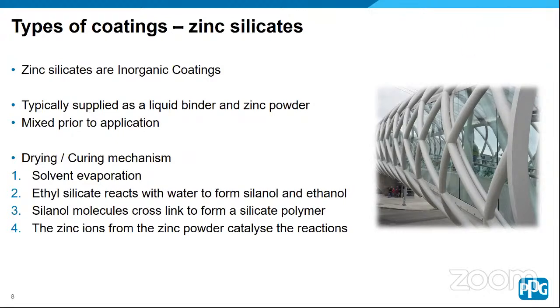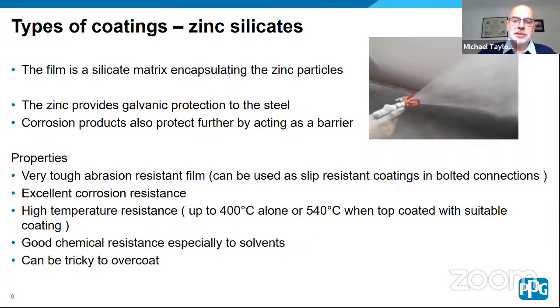Drying and curing mechanism, and you have the solvent evaporation first, and then the ethyl silicate reacts with water to form silanol and ethanol, and then the molecules cross-link to form a silicate polymer. And the zinc ions actually also catalyze the reaction as well. There are water-based zinc silicates as well, but this presentation mainly concentrates on the solvent-based ones. The film is a silicate matrix, and the zinc particles and the zinc dust are encapsulated into that matrix. And the zinc, as Martin mentioned, provides galvanic protection to the steel. With also, when you do get corrosion, some of the corrosion products are also insoluble, and they further protect by acting as a barrier. As Martin mentioned, the galvanic process only starts to occur once you have some damage through the coating to the steel. Before that, it does act as a barrier coating.